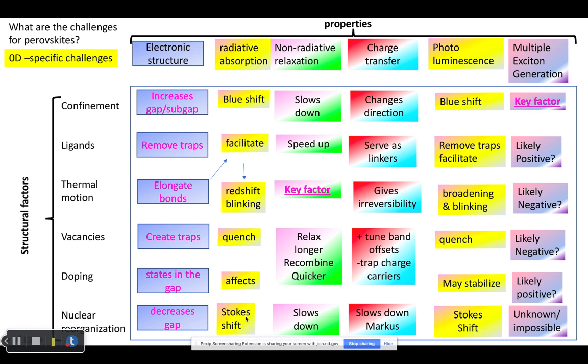For nuclear reorganization, optical properties reflect the so-called Stokes shift, meaning that absorption and emission happen at different frequencies, and non-radiative relaxation is slower, and charge transfer is typically slower due to the Marcus mechanism.